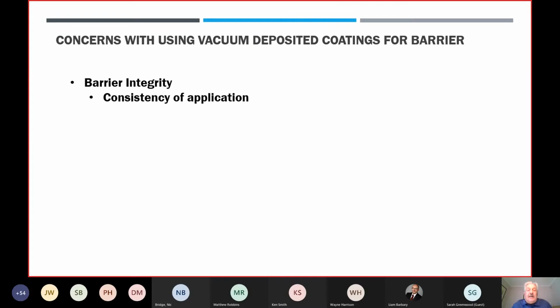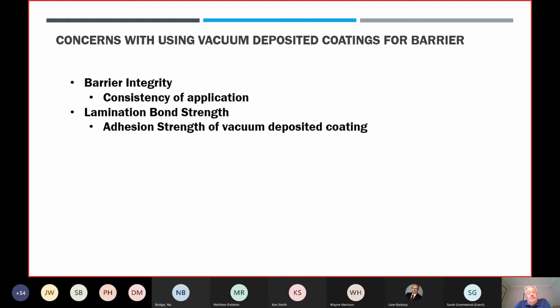Lots of people have concerns when using vacuum deposited coatings for barrier, and it all revolves around barrier integrity. You know, you've got a piece of foil in a structure and it looks very good. If it's got anything major wrong with it, like holes in that, it will tear in lamination. So you have a high degree of comfort factor. So consistency of application of the deposited coating is high in everybody's mind. And lamination bond strength, very important. How well is that coating sticking to the film that it's being applied to? And if it's not sticking very well, then there's a fair chance that your lamination will start to delaminate, and particularly for bigger packs, that really does become an issue.